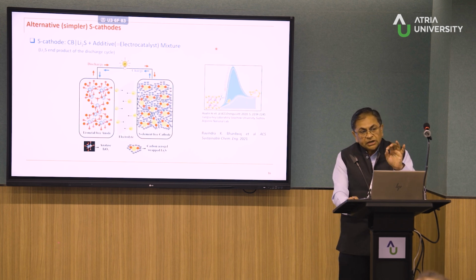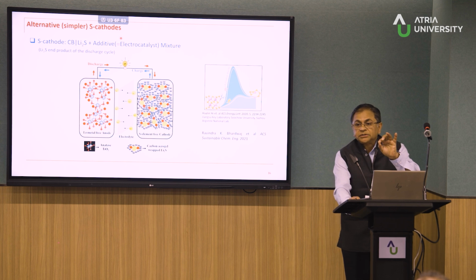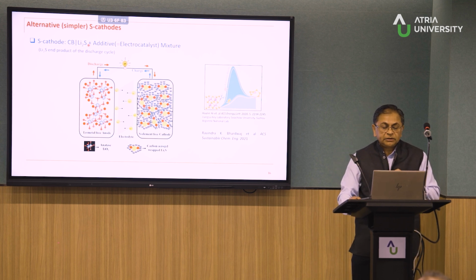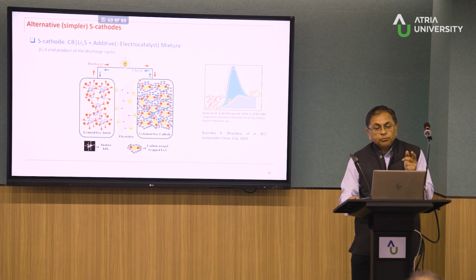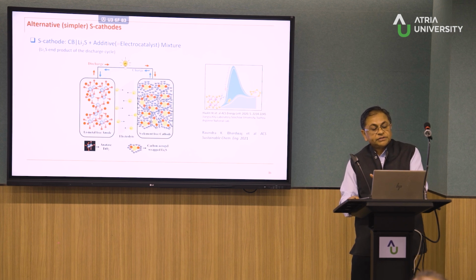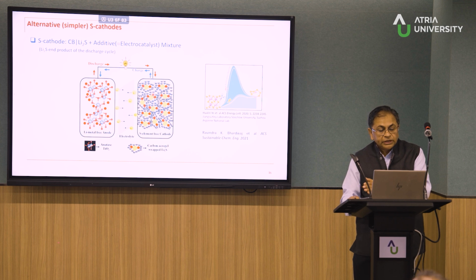Is that why we start with sulfur? Why not start with the end product of the reaction, like lithium sulfide? So what you immediately do is mitigate the volume change which takes place because of the conversion of sulfur to lithium sulfide. Okay, so you start with this.